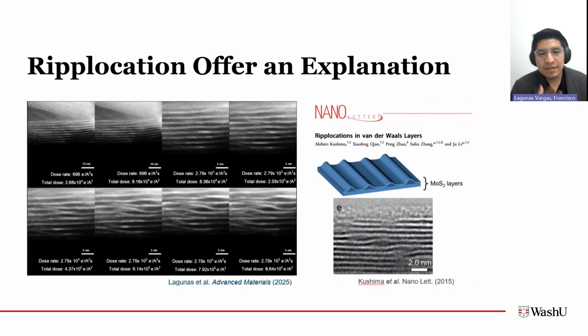So what is happening? We went through the literature. We tried to see if anyone else had seen similar effects to us. And we came across this paper in Nano Letters where a group had used a mechanical indentor to basically perturb these molybdenum sulfide 2D materials. And they formed these little ripples that propagated through the material, which they coined the term ripplocations. And if we look at our images and the images that they acquired from their materials, we can see that they resemble one another quite strongly.